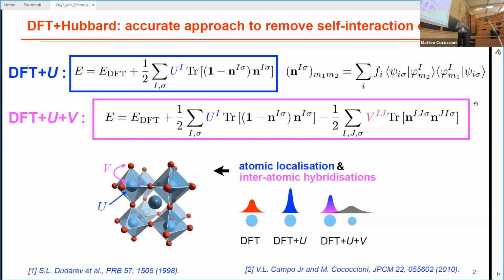Now the question is, what do I have if I have maximally localized Wannier functions? Do I need V or is it 0 V? Well, I don't know, but if V is 0, this means the Wannier orbitals are such that they still have that nature of covalency somehow. I don't know if this makes sense, but to me, if you have 0 V in the basis of Wannier functions, maximally localized Wannier functions, it means your Wannier functions are such that you have that covalency there.